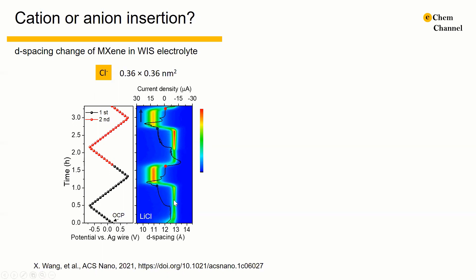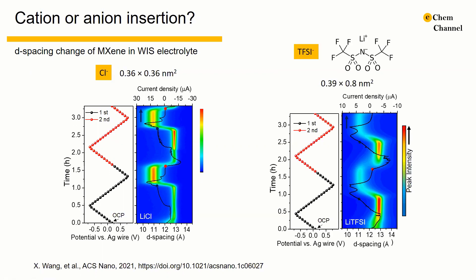The dramatic shrinkage of the interlayer space at the anodic peak and expansion at the cathodic peak indicates that anion intercalation and de-intercalation does not play a role in the observed electrochemical process. When 21 mol/kg lithium TFSI was used as the electrolyte, approximately the same trend and magnitude of change in d-spacing were observed. But we know that the size of the TFSI anion is much larger than the chloride ion. This further rules out the possibility of anion intercalation. Hence, the peaks in the CV in the water-in-salt electrolyte are accompanied by lithium ion intercalation instead of anion intercalation.